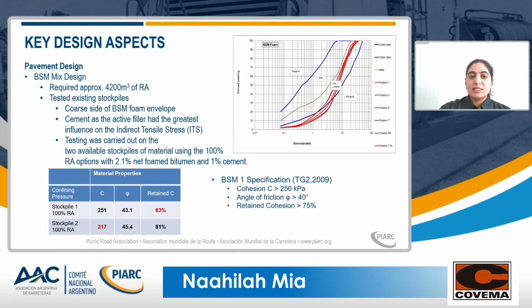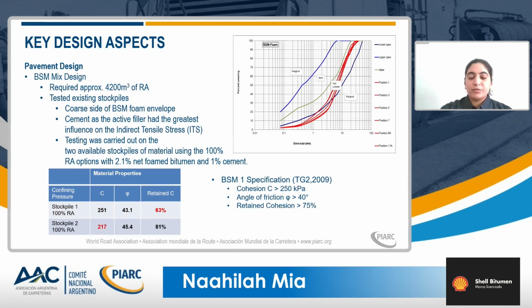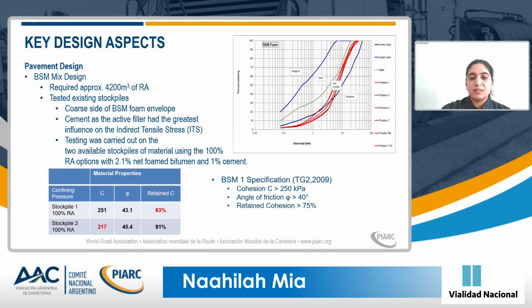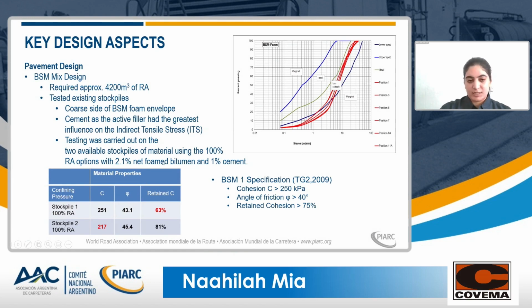ITS testing was carried out on 2 available stockpiles of the material using 100% RA options with 2.1% net foam bitumen and 1% cement. From the 2 stockpiles, the tests indicated that for stockpile 1 the cohesion was 251 kilopascals, the angle of friction was 43.1 degrees, and the retained cohesion was 63%. In stockpile 2, the cohesion was 217 kilopascals, the angle of friction was 45.4, and the retained cohesion was 81%. Per the South African standards, we can see that in stockpile 1 the retained cohesion did not meet the standard, and in stockpile 2 the cohesion did not meet the standards that we require.